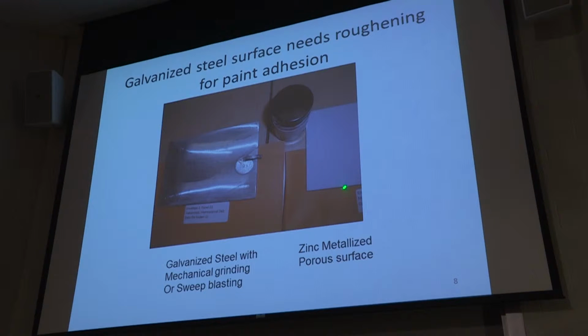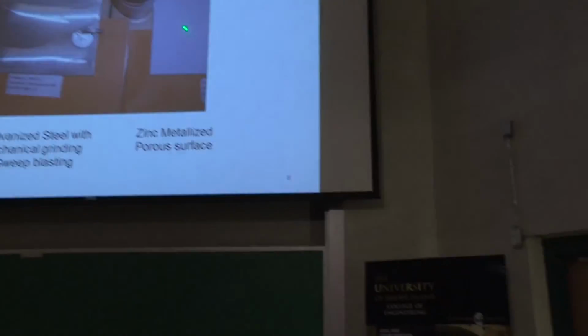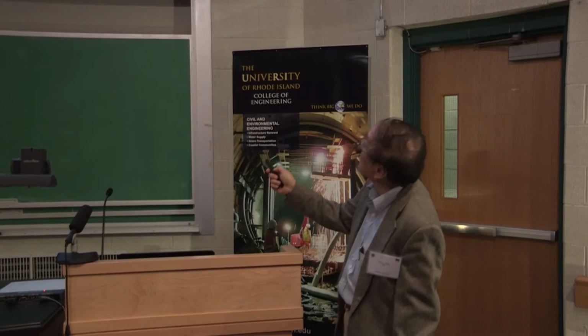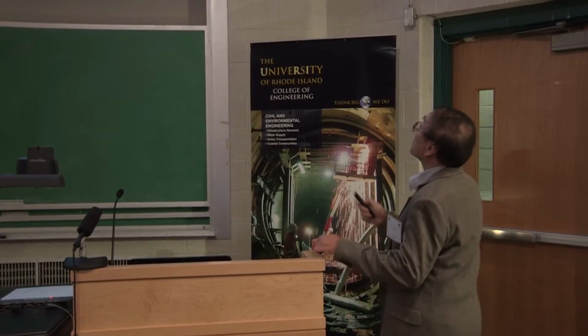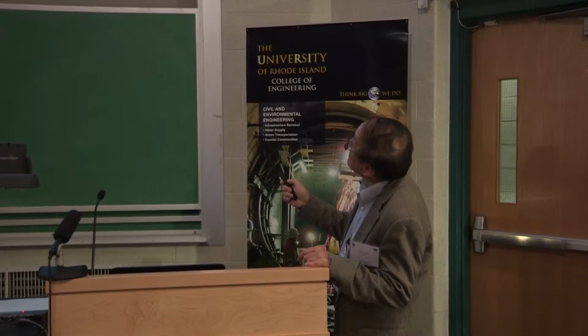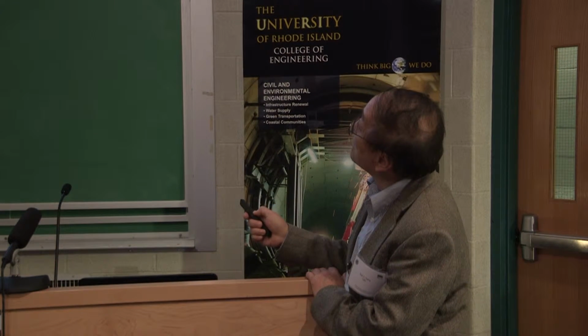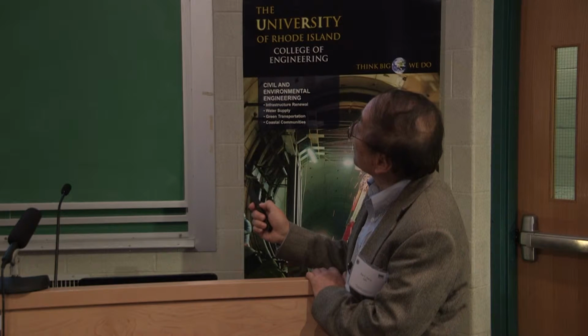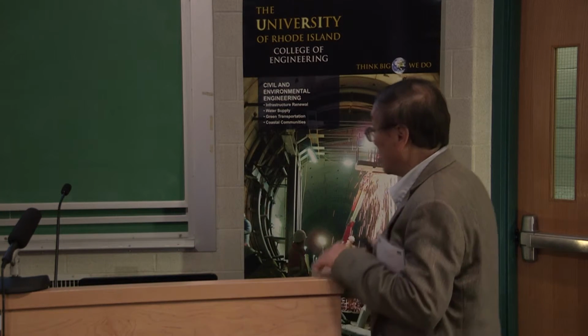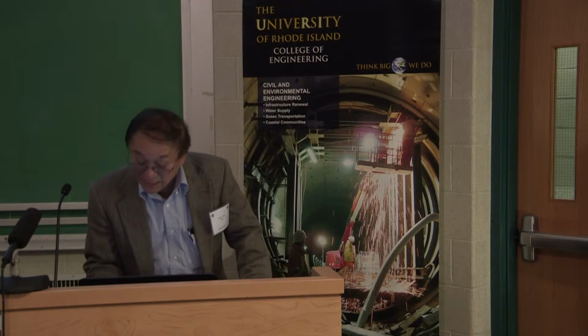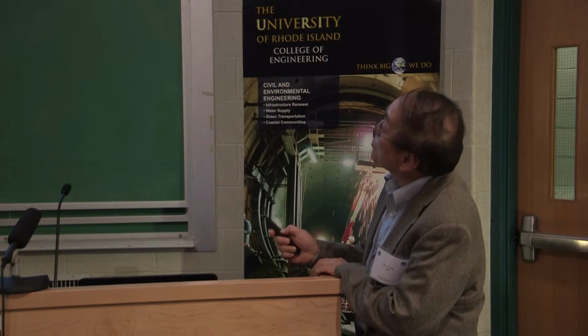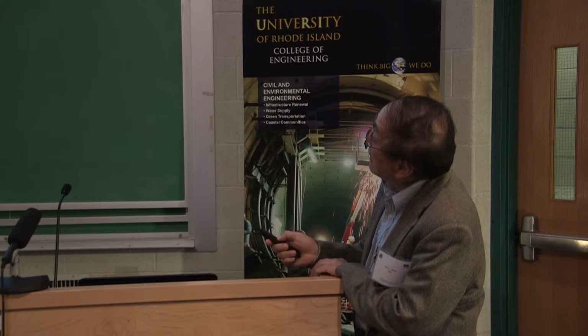And this is a steel plate with the zinc thermal spraying on it, and you can see this surface is rough, and the reflection on it. The sweep blast coating is a little lighter in color than this thermal spray, and these are the initial zinc coated substrates. Then we go through using these test panels and perform coating on them.